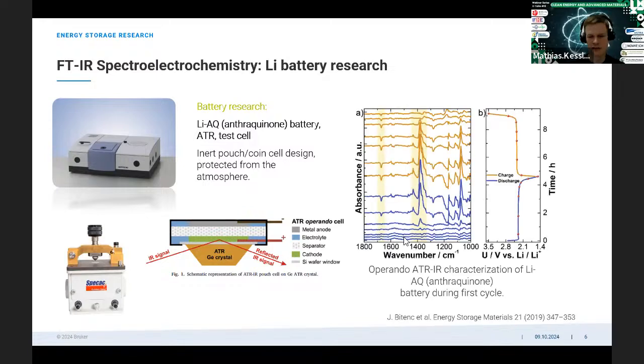And for example, on the right side, then the resulting spectra is shown during the charging process and the discharging process. And then we see how the organic redox pair in solution changes on the surface of the electrode. So we can directly observe these reactions inside of a battery cell.